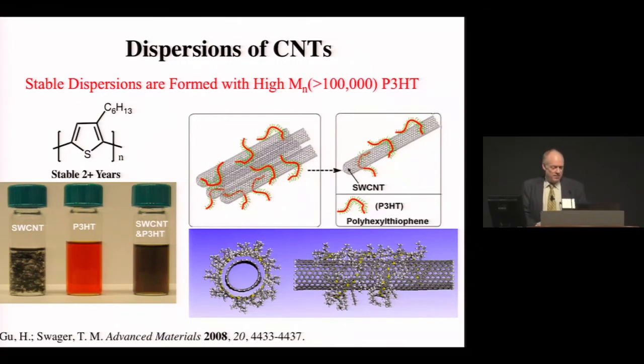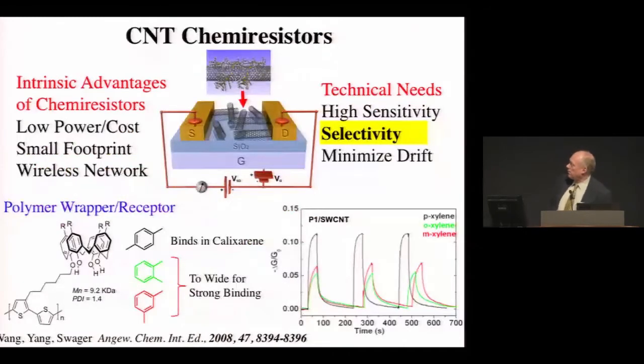So we did that. Now this is kind of a boring polymer to use, but you can do the same thing with polythiophenes that we've basically modified to make things that are starting to look like receptors on them. And so here's one that uses something called a calixarene. It has the shape of a small bucket type molecule. And when you put tert-butyl groups here, these are big hydrocarbon units, what you can do is you can find that these will bind xylenes. These are different isomers of xylene.